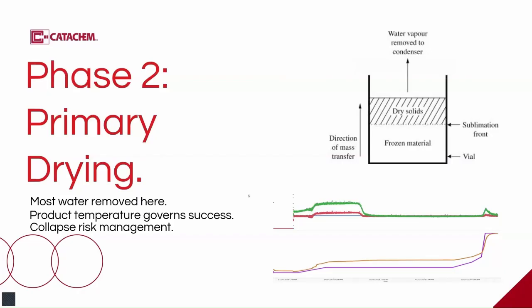This is where people can make two common mistakes. First, they monitor chamber conditions and assume the product follows. It does not always follow. Second, they push shelf temperature for speed without truly knowing the product's thermal limits. At Catachem, primary drying is controlled around product temperature, not just shelf temperature. We use product probes and cycle analytics to ensure the product stays within its safe window. The goal is not as hot as possible. The goal is as warm as allowed safely, because that's how you balance throughput with protection.